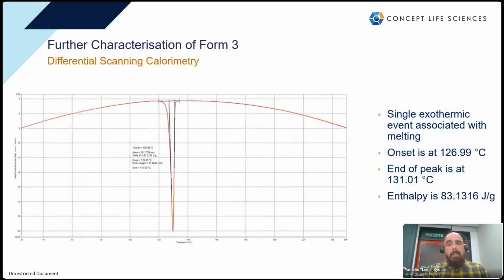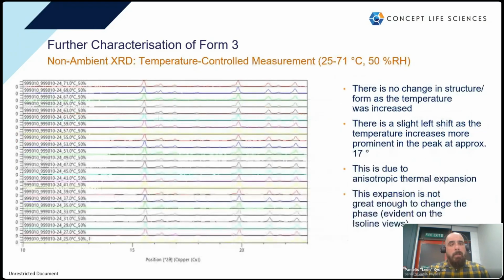Moving on, doing the same with DSC, we only see one transition at 127 degrees Celsius, which can be attributed to a melting event. Again, the one thing that we can take from these two is that we only have probably one form here, but further on, we suggested that we use our non-ambient XRD to examine the stability of the form. So the first experiment we ran a temperature-controlled measurement, ramping up from 25 degrees to 71 degrees at 50% relative humidity.